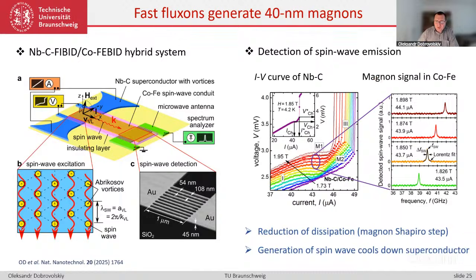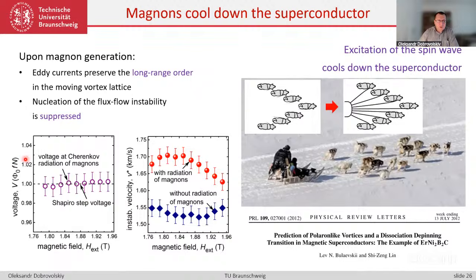So basically here we take a look at the voltage, and this voltage corresponding to the Shapiro step is expressed in units where we know the number of fluxons and we know the spin wave frequency. So this is very similar to the Josephson relation, just frequency and phi naught, as in a Josephson junction. But here, in addition to that, we have the number of fluxons. If we have the Josephson effect, we have a relation of the frequency of electromagnetic radiation and voltage, linked by the fundamental Josephson constant, basically 1 over phi naught. In our case, it is the same fundamental constant of magnetic flux quanta, the Josephson constant. But in addition to that, we have the number of fluxons. That means that all fluxons which are available in our system contribute coherently, but now instead of the frequency of electromagnetic radiation, we have the spin wave frequency. The rest, the voltage over the superconductor, is the same.